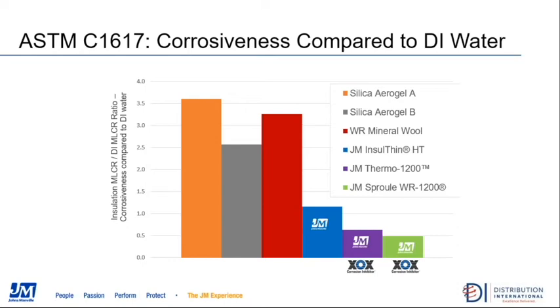And the Johns Manville Thermo 1200 calcium silicate and Sproule WR 1200 perlite products actually have a corrosion rate much better than that of the DI water baseline, shown by the ratio of less than 1. And that is the result of that active corrosion inhibitor that is included in both of those products.